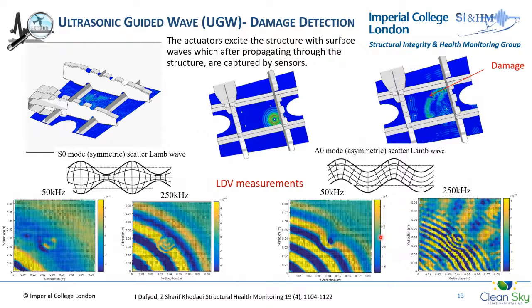But most of the detection algorithms are baseline methods. So it means that when you sensorize your structure, you record the baseline at a healthy state. So you know when there is no damage, you record the response of the structure. And after a while, at the current state, if you want to detect whether there is damage or not, or check the integrity of the structure, you retake these measurements and you compare the current state with the baseline state.